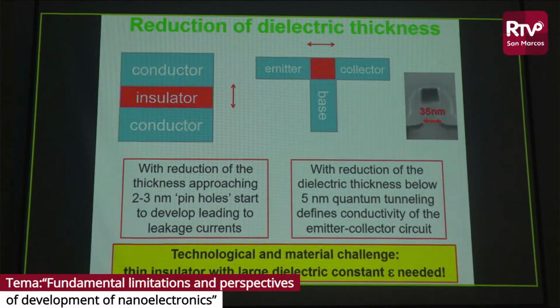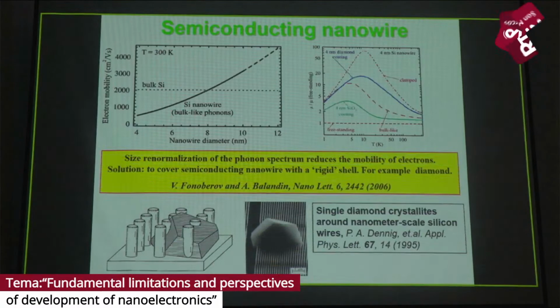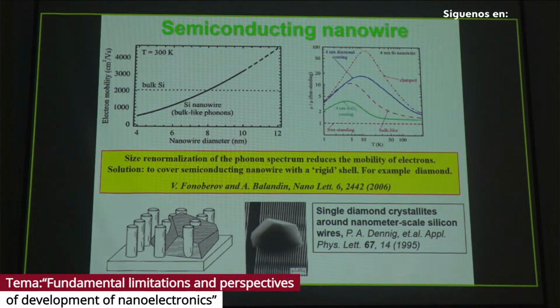So it's a big challenge for technology to overcome these limitations in semiconductors. Even more, if we look at the dependence of the mobility of silicon, which is the most commonly used semiconductor, it appears that, for example, the mobility of charge carriers in a nanowire below 8 nanometers is already smaller than in the bulk. And it's due to problems with the electron-phonon spectrum in such ultra-small silicon nanowires.